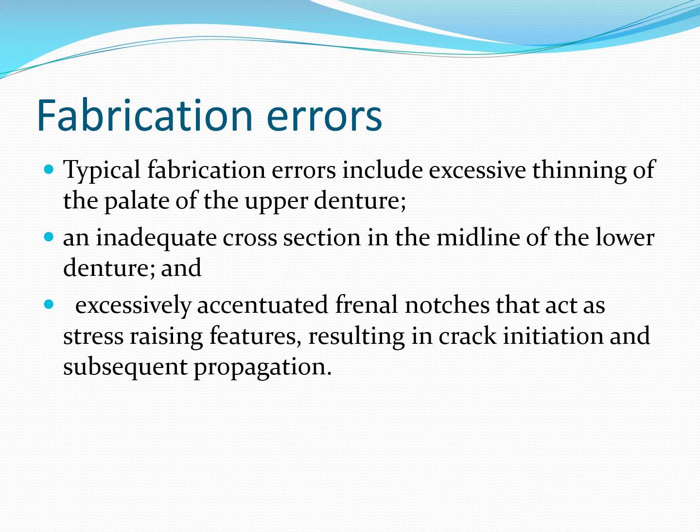An inadequate cross section in the midline of the lower denture, and excessively accentuated frenal notches that act as stress raising features, resulting in crack initiation and subsequent propagation.